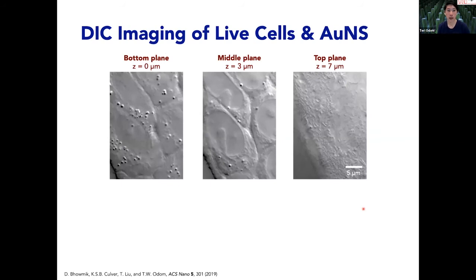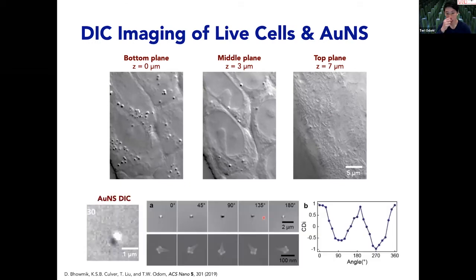So this is what the DIC image looks like of live cells. And so this is the bottom plane, the middle plane, and the top plane. And so you can see here also, as you just change the orientation over 180 degrees, you go from mostly bright, because this is the dominant mode, to dark to bright.